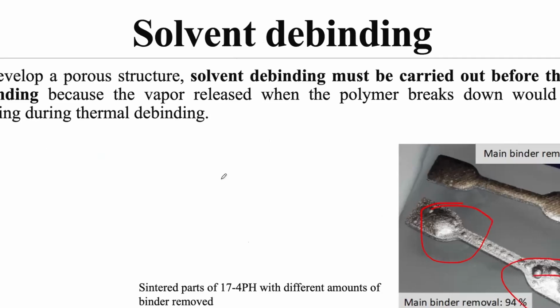Imagine when solvent debinding is happening. What essentially is happening? Pores are getting created. Okay, and these pores act as the escape route for everything else to come out and vaporize when the final sintering is happening. If these pores or channels are missing, what will happen? Everything which is inside will try to vaporize, and because it will not see any escape route, you will see blisters like this, which is a very common defect in this particular type of process.